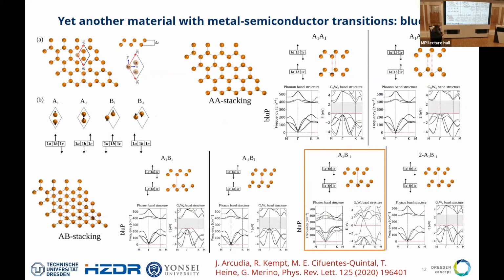Good. So are there more materials like that? Here's a very recent example, blue phosphorus. Blue phosphorus has been suggested by David Tomanek, and has been made very recently. Essentially, you think about graphene, you replace the carbons with phosphorus, but then you have some buckling. Every second phosphorus is above the plane and every second is below the plane. That means that if you stack them together to a bilayer, you're not only having AA and AB, you also have to take care about the positions of these 2 atoms.